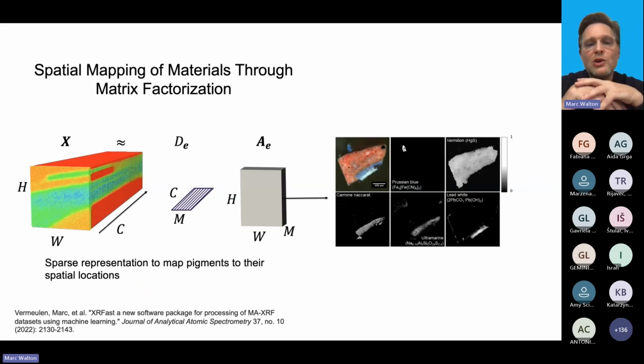And of course, the reason that we want to do this type of work is to be able to make these measurements, each one of these angular measurements, at a variety of different wavelengths, starting at 400 nanometers and then collecting every 5 nanometers across the visible spectrum. So going from 400 to 1,000 nanometers, which creates a hyperspectral cube, which we can then factorize and determine the end members. So we can map pigment phases across a cross-section.